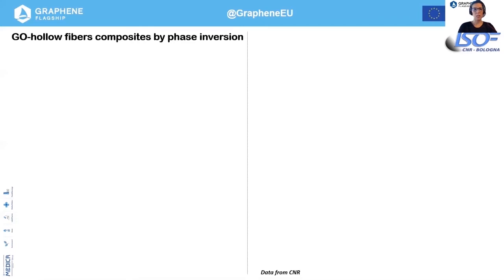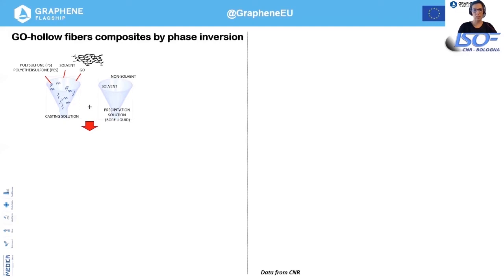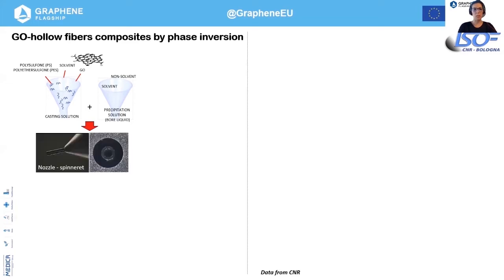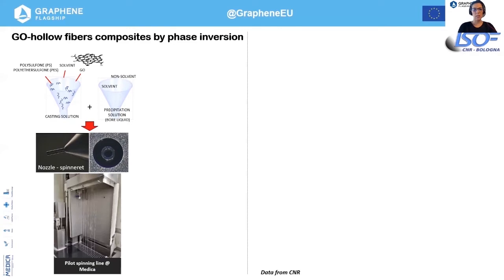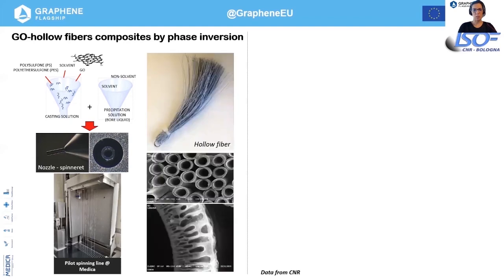The first one is to act directly during the phase inversion process, during which hollow fibers are formed. Practically and briefly, we put graphene oxide together with a solvent and polymer, that in this case is polysulfone or polyether sulfone. These compounds are mixed together to create the casting solution. This casting solution, together with bore liquid, is fed to a spinning nozzle, and when these solutions meet, they form the hollow fiber by phase inversion.